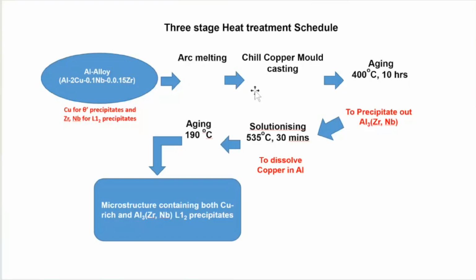The schedule is, we arc melted and chill cast the alloy, then aged it for 10 hours at 400 degrees centigrade. This is still the cast structure, and after 400 degrees centigrade for 10 hours, we precipitate out the ordered precipitate, and then we upquench it to solutionize. I'll show you what happens when you do upquench. And then, of course, classically age it, and aluminum copper alloys normally age at 190, so that we have done.